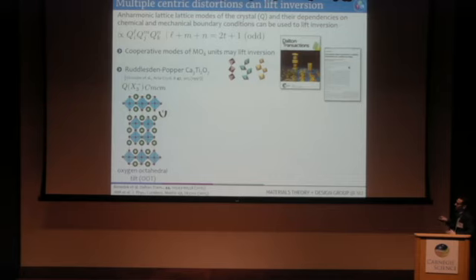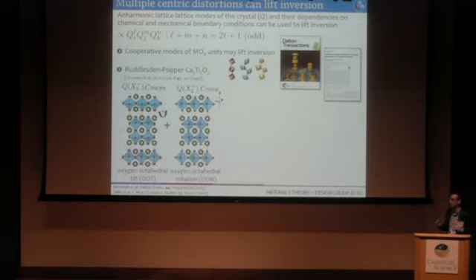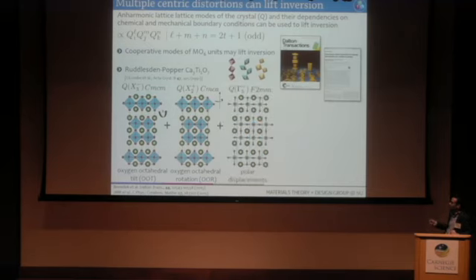There's one mode here, which looks like oxygen octahedra tilting about this axis. So if you focus on the red oxide anions, you can see them tilting. Okay, this mode, just like all of general tilt modes by itself, preserves inversion symmetry. Okay, it combines with another type of rotation of octahedra, and it's a rotation along the tetragonal axis. So if you focus on the equatorial oxygens, you can see them moving in or out of phase. Again, an inversion symmetry preserving distortion, but in combination, they break the necessary symmetries for inversion, and they allow polar types of distortions here in the calcium and then in the titanium oxide layers. So ultimately, you do obtain a structure without inversion symmetry, and this material is now referred to as a type of hybrid improper ferroelectric.